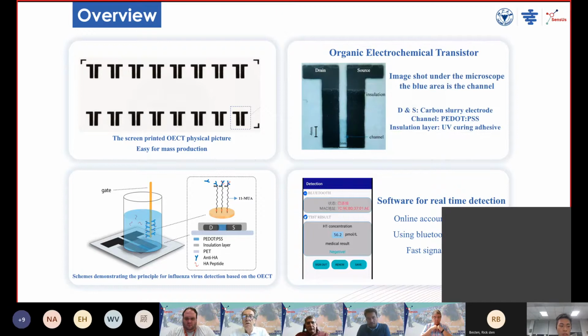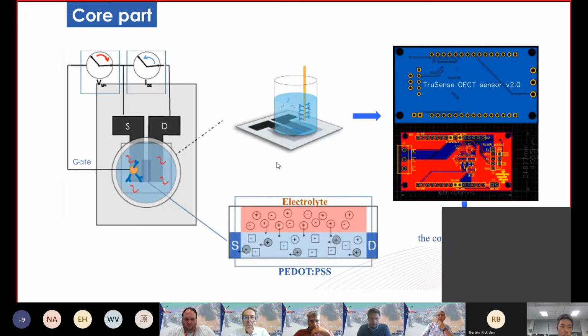Concerning the detection of the biosensor, we firstly explored a classical way of using a gold electrode with antibody as a probe and 11-MUA for cross-linking. As illustrated, if the amount of HA peptides captured by the antibody changes, the voltage of the gate will change too, resulting in more or less ion injection into the semiconductor, which will influence the conductivity of the semiconductor too. Then the current between the source and the drain electrode will consequently vary, and the signal will be detected by the circuit of our own design. Then it automatically transfers the current signal into the concentration of the virus by the program.